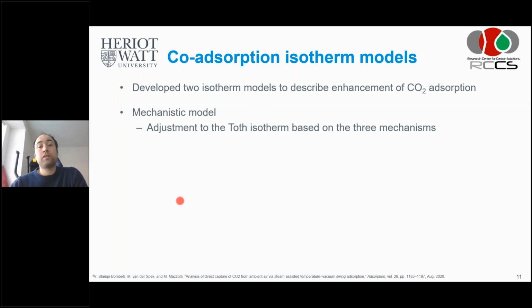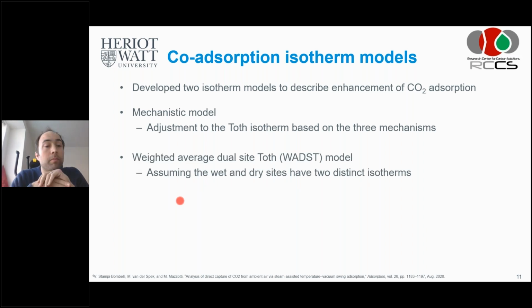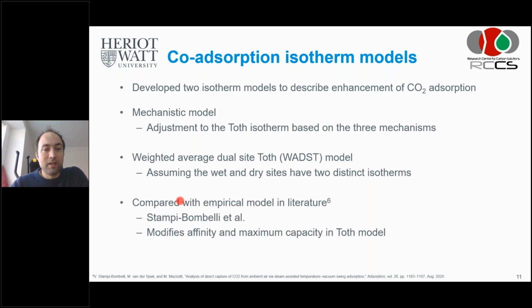Now, what we did is we developed 2 isotherm models. One is mechanistic, so it completely follows the mechanisms that I showed earlier, the chemistry and the site blockage. The other one is a little bit simpler, more empirical. A weighted average dual site Toth model is what we call it, where we assume that the wet and dry sites have 2 distinct isotherms, and with the distribution function, you assign how much of each isotherm is present, given a certain relative humidity. We also compared it with an empirical model that was available in the literature, the first such model for an amine functionalized group. Also work that I was involved in.